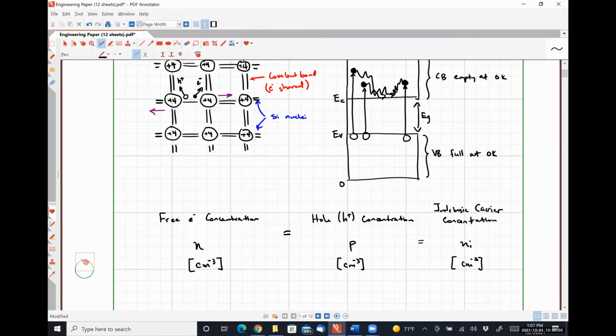These are all statistical things based on Boltzmann statistics, their probabilities. And the value is not something that's set in stone, okay? Different pieces of literature refer to it as significantly different values, but it's usually going to lie somewhere between 1 to 2 times 10 to the 10 atoms per centimeter cubed.